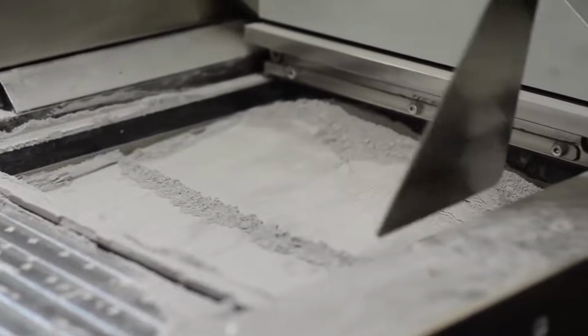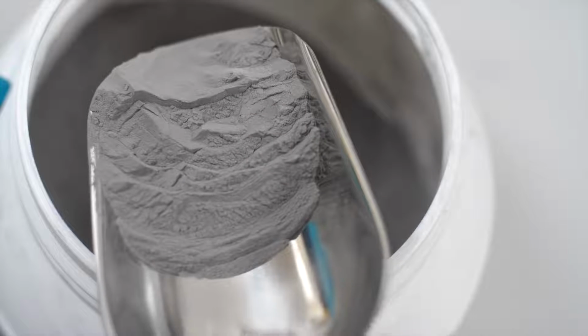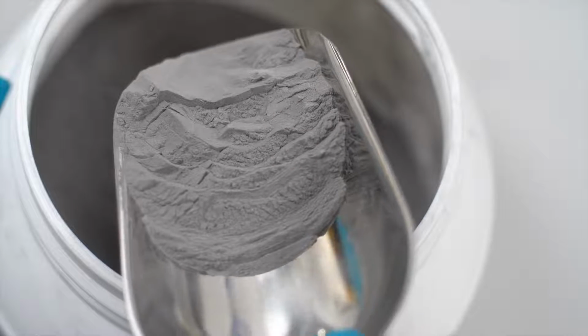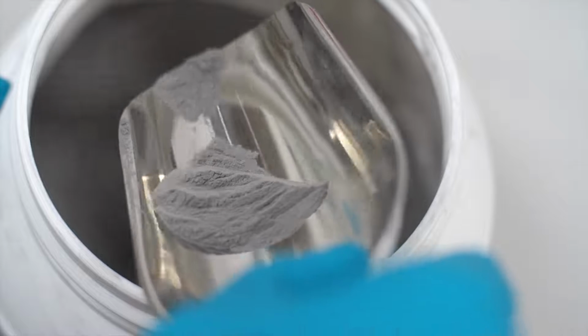We got a clearer look at why this happens when researchers used high-speed synchrotron X-ray imaging to get this phenomenal footage of the laser melting process, which revealed many of the phenomena resulting in imperfections. Here, we have a powder bed of iron-nickel alloy called Invar 36, which has been turned into a powder by blasting a stream of molten metal with a high-pressure gas. This process is called atomization.